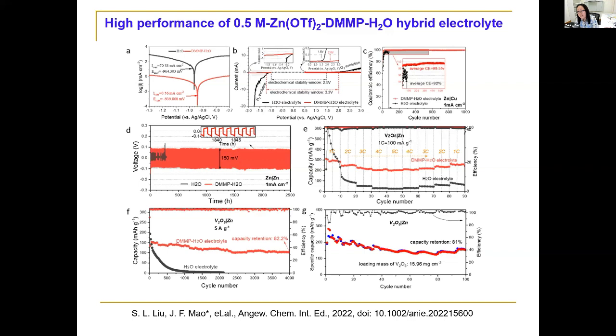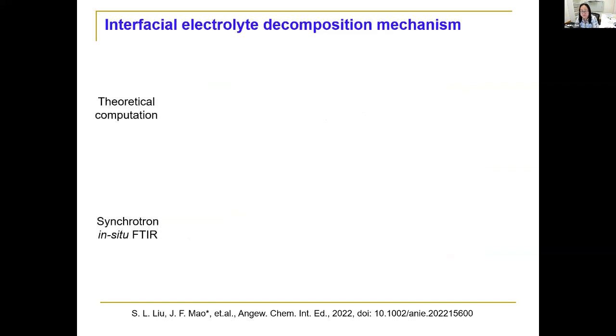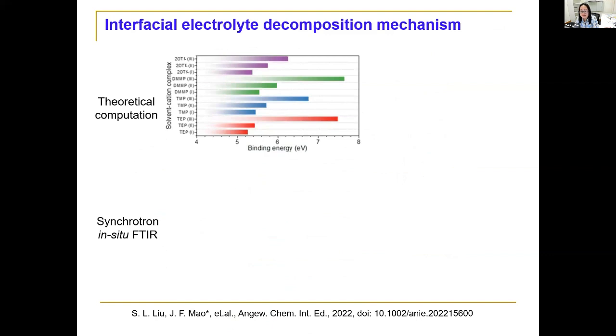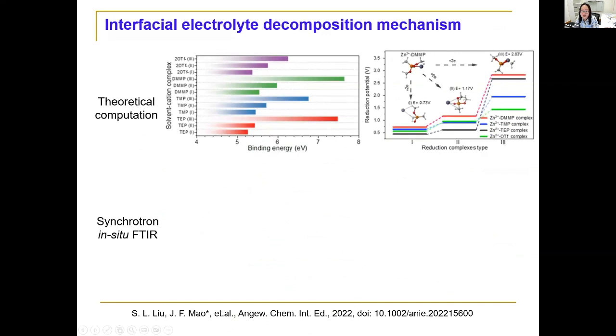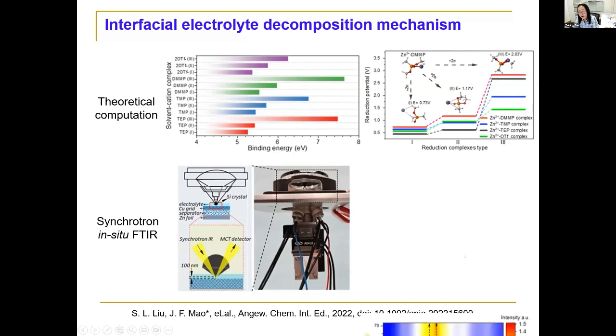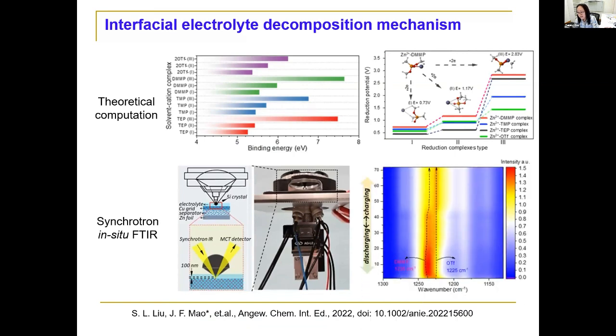So this DMMP-water hybrid electrolyte has very good performance when used as the electrolyte for zinc-ion batteries. Then, to understand why the DMMP-water hybrid electrolyte performs so well, we did a theoretical computation and found that in the solvation, DMMP strongly interacts with the zinc ion, stronger than the other solvents. And also from the in situ FTIR, the concentration of DMMP at the interface is quite high. And once it is charged, the concentration reduces, therefore suggesting DMMP is the main component that decomposes at the interface.